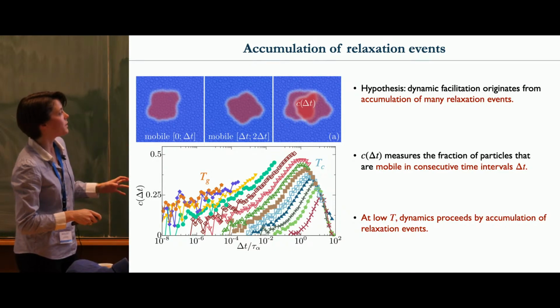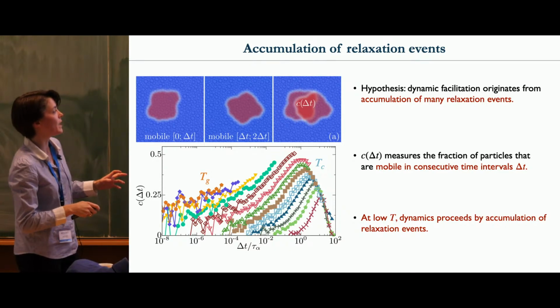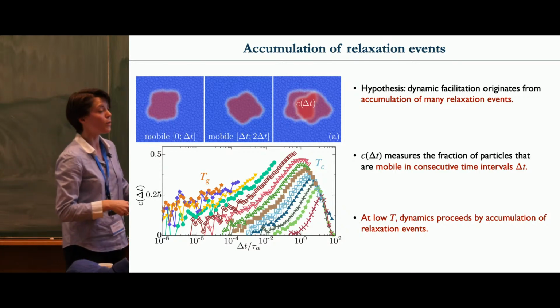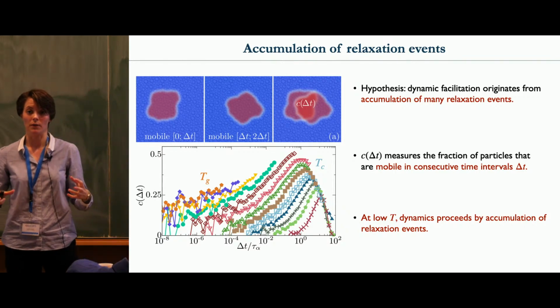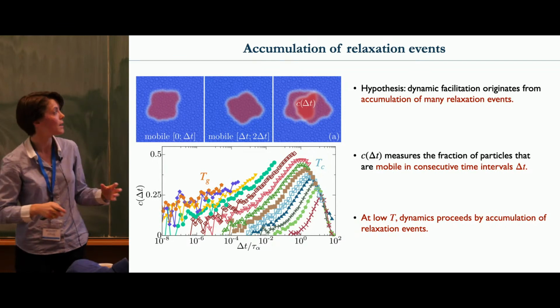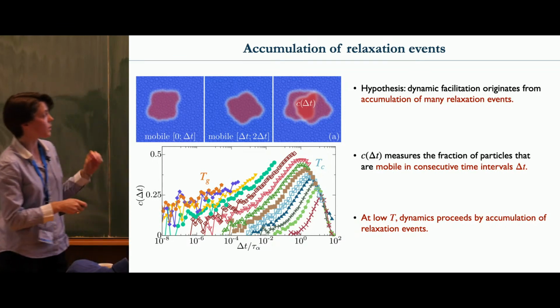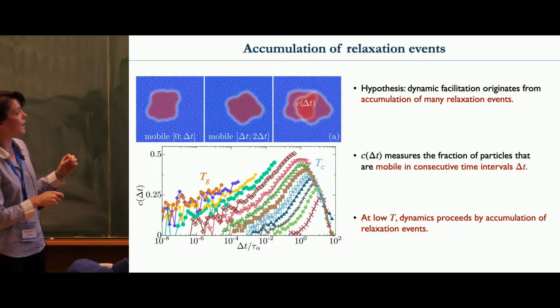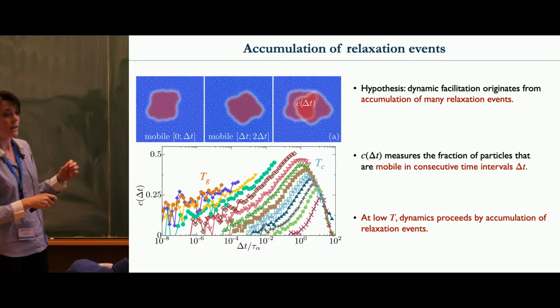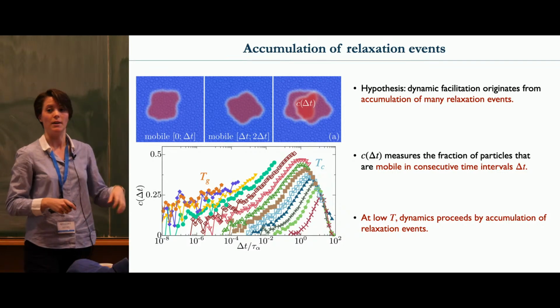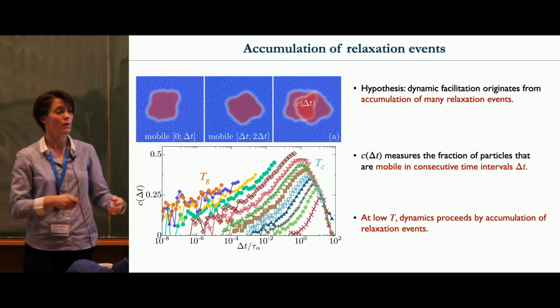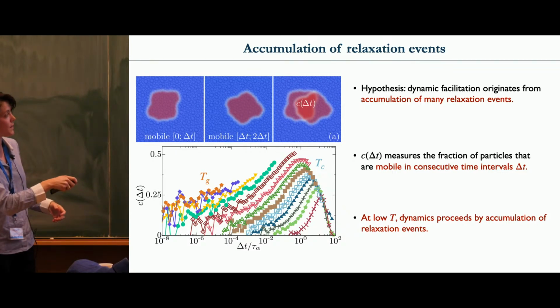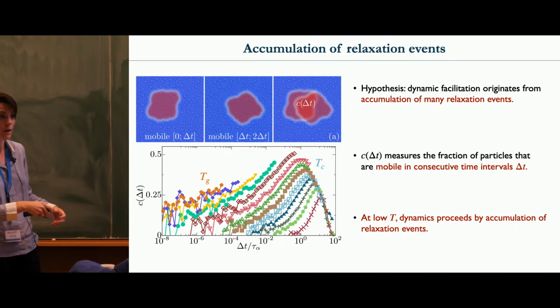And what you should see here is that the timescale on which the dynamic repeats itself the most is actually the alpha relaxation time, so when half of the particles have relaxed. But most importantly, what I want to really stress here is that at low temperatures close to the experimental glass transition, also at extremely short time scale, the dynamics is highly repetitive. So the fact that this value here is high even at extremely short time scales compared to tau alpha.